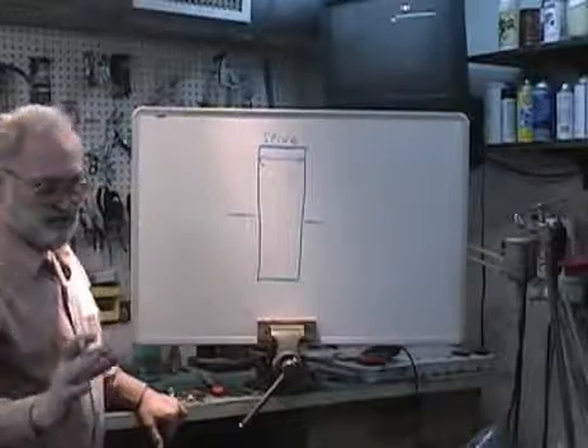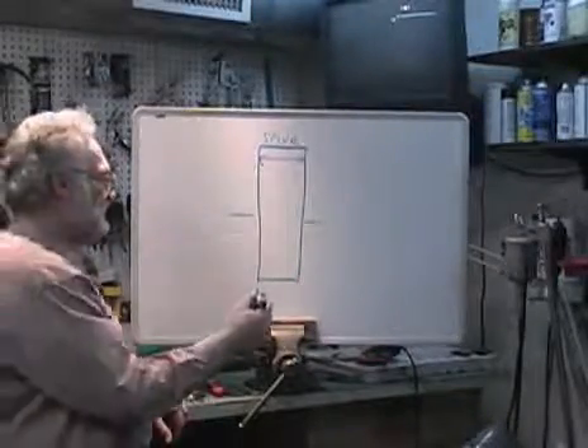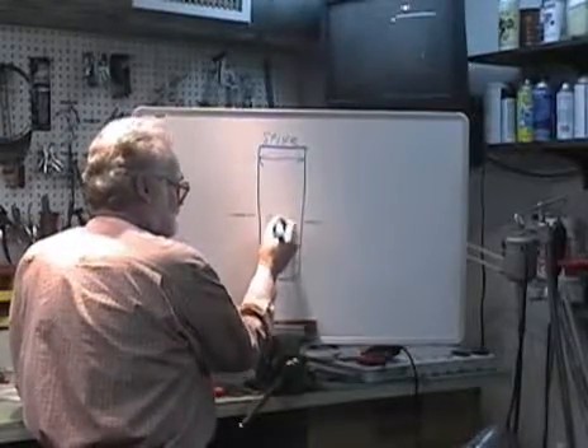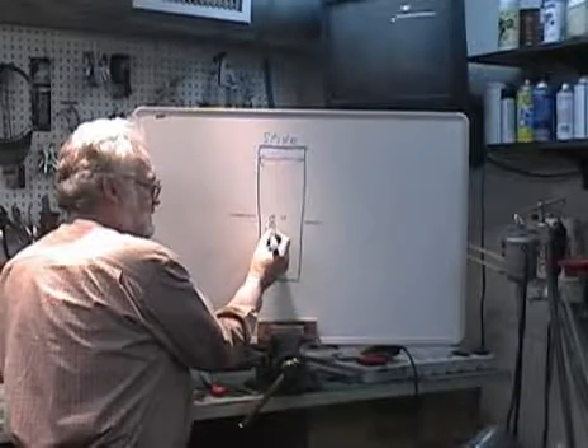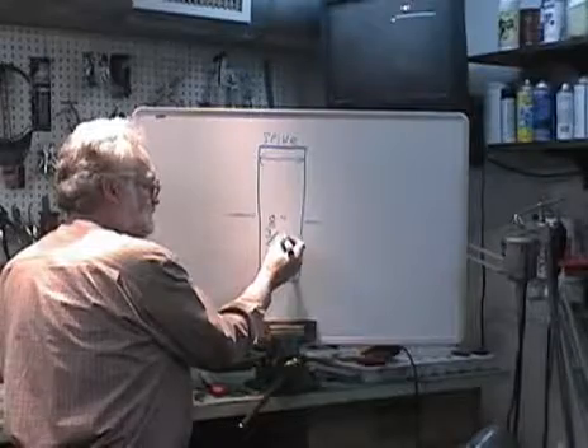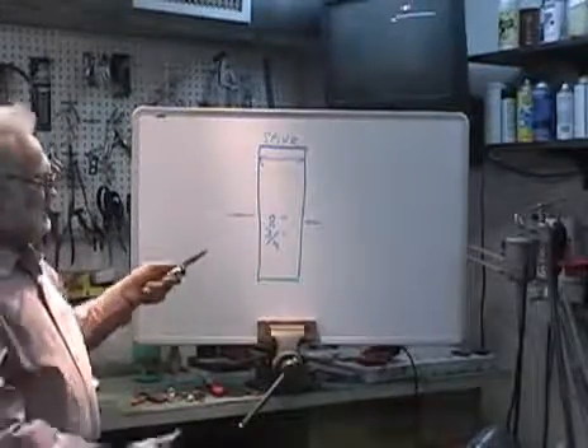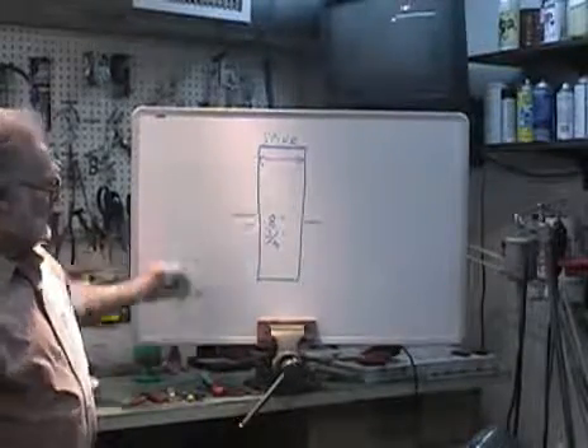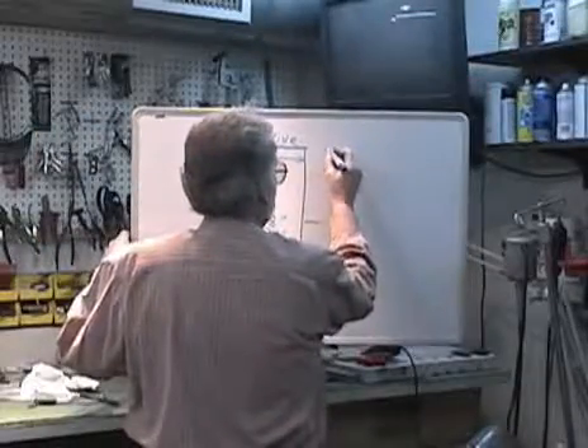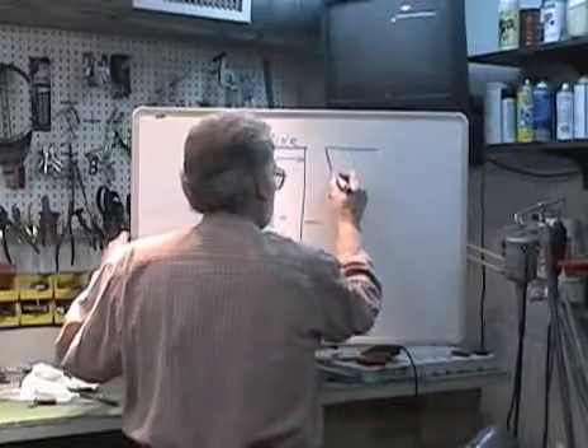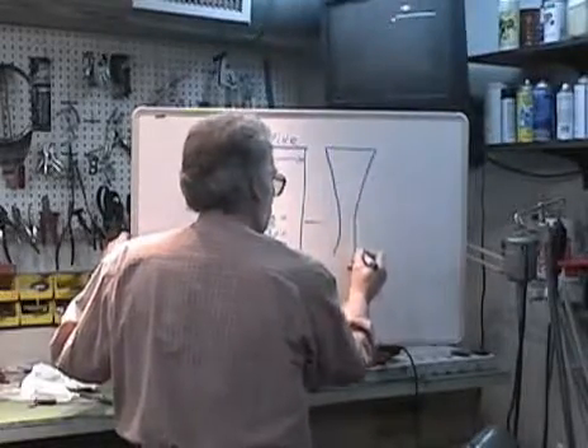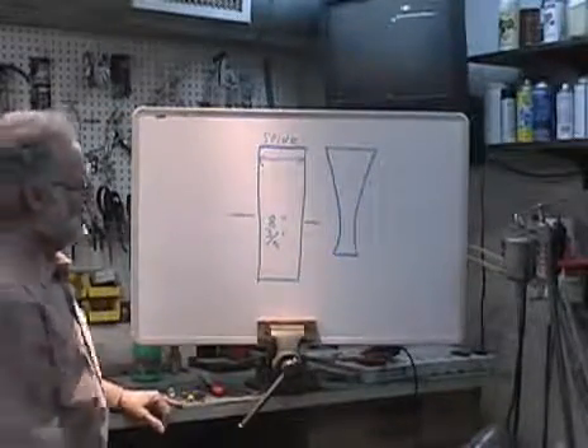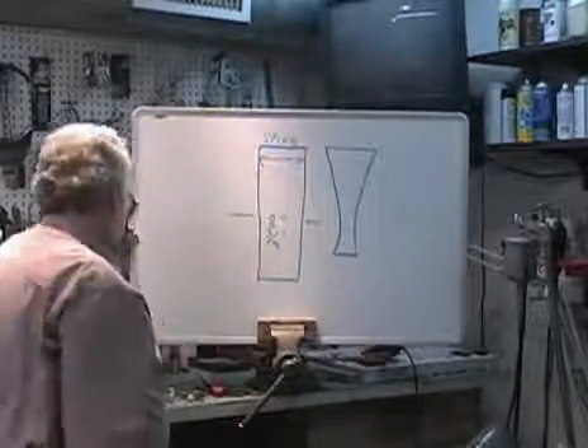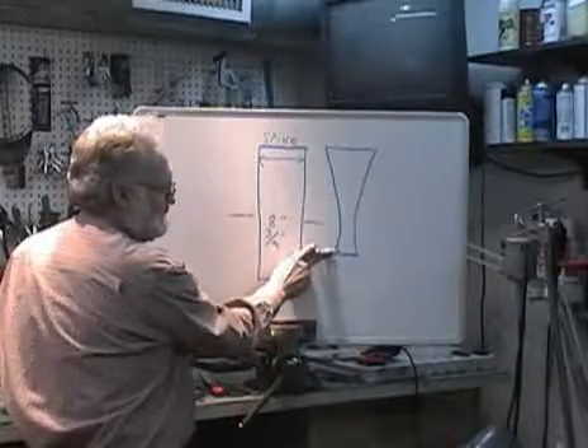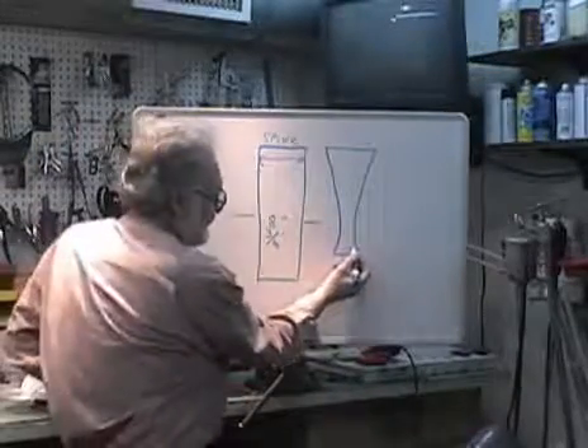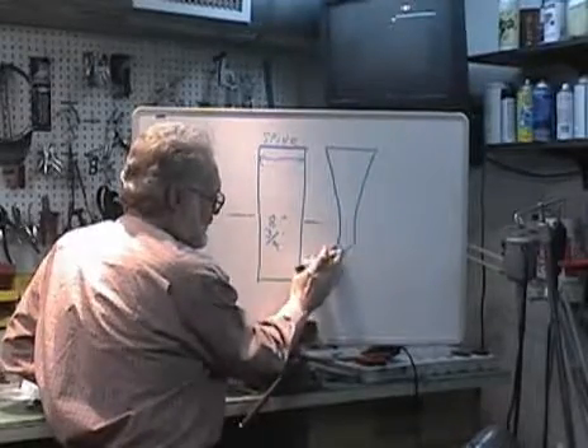I'm going to give you some rough estimates because, like I said, I don't have the formula in front of me. But for an 8-inch wheel, you can grind approximately 3/4 of an inch. Now, if you try to grind higher than that, I'll show you what happens. And this is very extreme. If you start trying to grind higher with the smaller wheel, you'll start getting an hourglass effect on your blade. And then you have this situation right here.